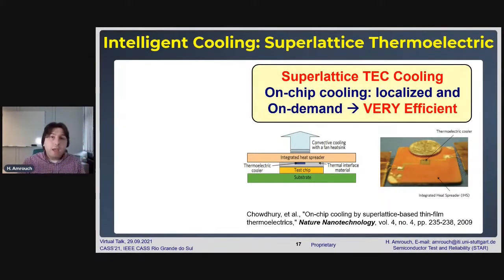The breakthrough that came in the last decade is through inventing a way to fabricate the thermoelectric devices as ultra thin films, or superlattices. The thickness of them is just 50 micrometers, for instance. And by integrating them within the chip die, we are able to put them where the hotspot is generated, and then we can cool down only the hotspot, paying the cooling cost only at that location.